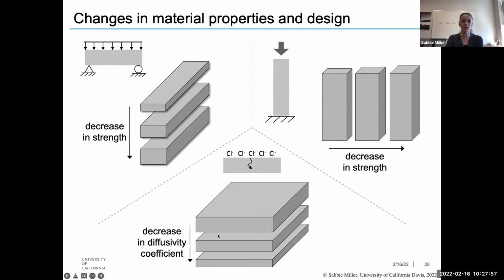So here I'm showing chloride ingress, where basically if we are able to get a material that has a lower diffusion coefficient, then again, perhaps we could get away with a slightly different concrete cover, or perhaps not have to replace the material as frequently if it does have exposure to salts. So the mentality here is that we could potentially change the volume of our concrete necessary for any given application if we specify a different input in terms of the properties necessary.